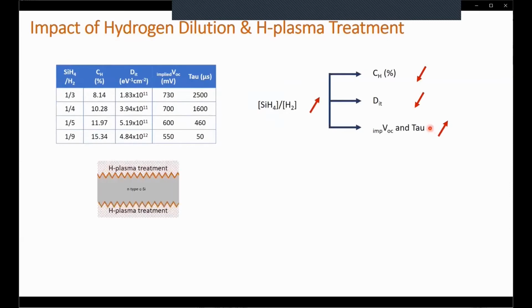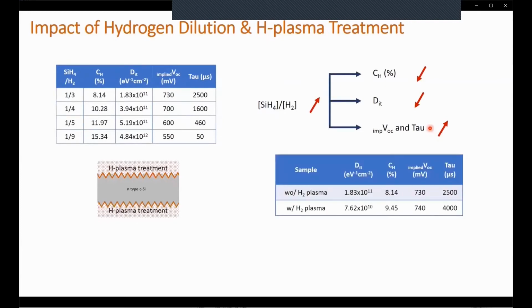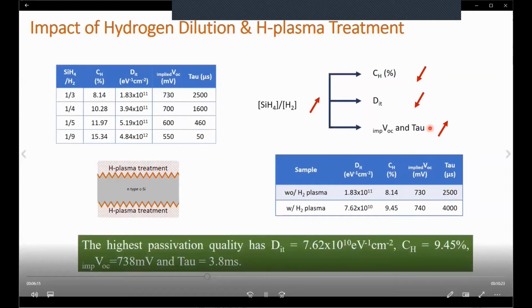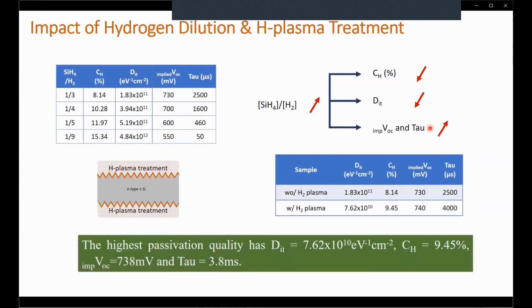When we add hydrogen plasma treatment with optimum values, interface trap densities decrease and hydrogen content increases. So with hydrogen plasma treatment, it's possible to bond dangling bonds on the interface, which results in lower interface trap density. At this stage, we found the highest effective lifetime of 3.8 milliseconds.